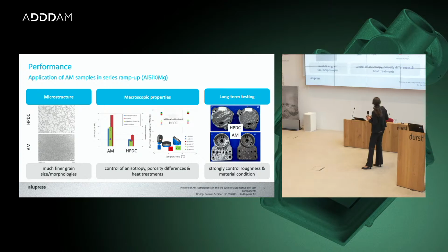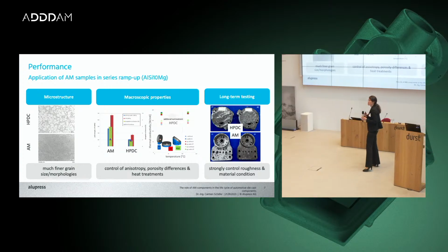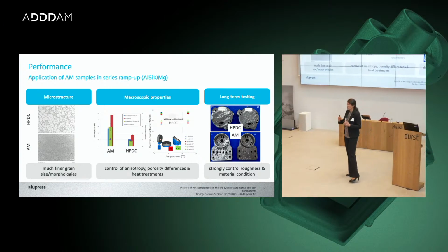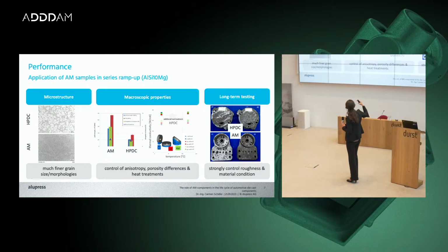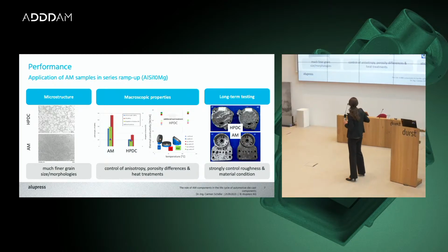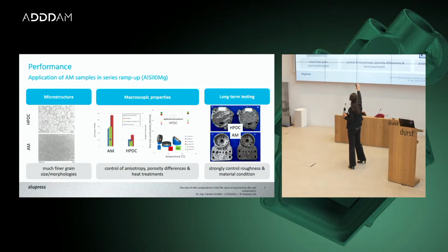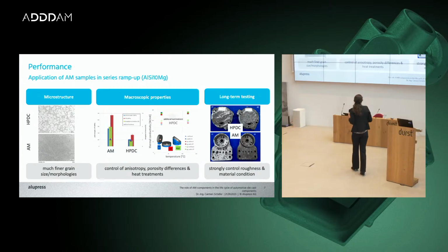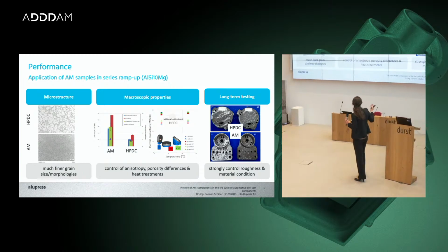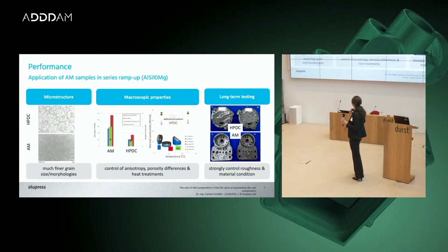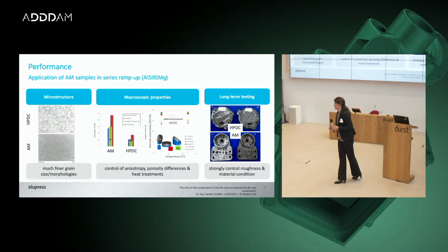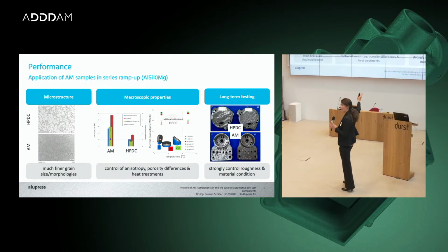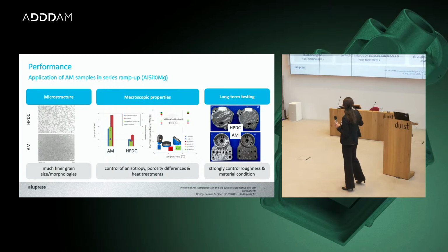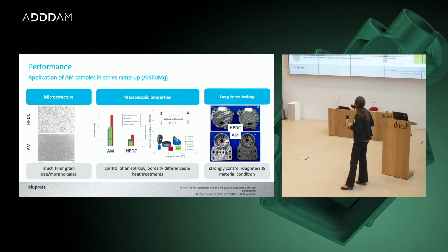And you can see it here on the right hand side, for example, for the thermal conductivity. Also this, if you need to preheat your building stage, or you want to change the thermal conductivity on purpose, you need to consider the building direction in AM. On the right-hand side, we have also the issue of roughness or material condition if you go in a long-term testing. This works fine, it agrees very well, and you need to consider this.